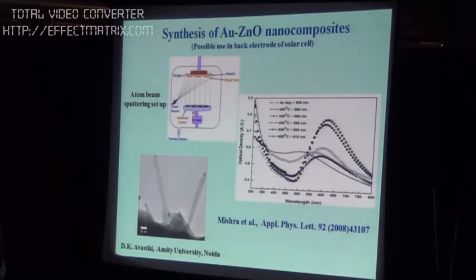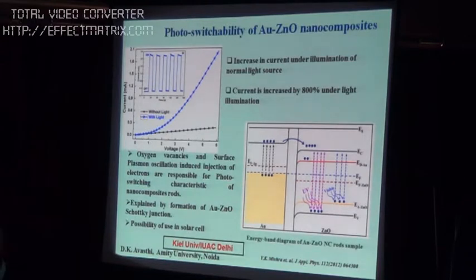Further study was done, where you do the IV characteristic in the dark, and you get this curve. When you shine light, the current increases, which means you are able to create more current, more electrons, in the presence of light. That means it has the capability of producing more electrons in the circuit, and this is shown here. Current is here, when you shine light it goes up, you remove the light it goes down, and so on. So it is repeating, and it could be explained by the band diagram, but the important message is that this gold zinc oxide is something like a Schottky barrier, a metal sitting on a semiconductor, and in the presence of light the electrons in the circuit are increased.